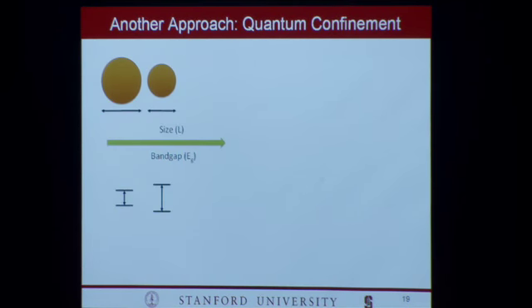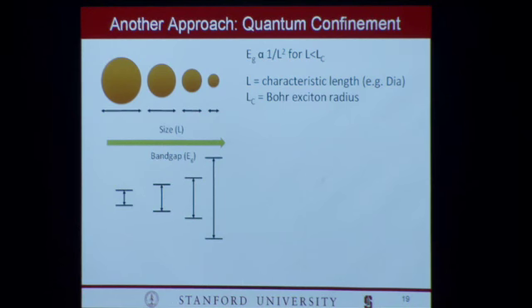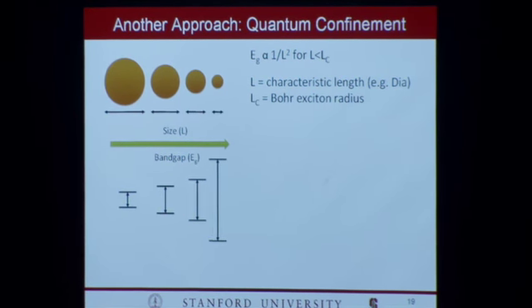So our approach, we're going to look to a different approach than one that has traditionally been used in the literature, and that is that of quantum-confined semiconductors. And the idea here is that if you take a semiconductor and shrink its size below what's known as the Bohr-exciton radius, you can actually increase the band gap of your semiconductor.